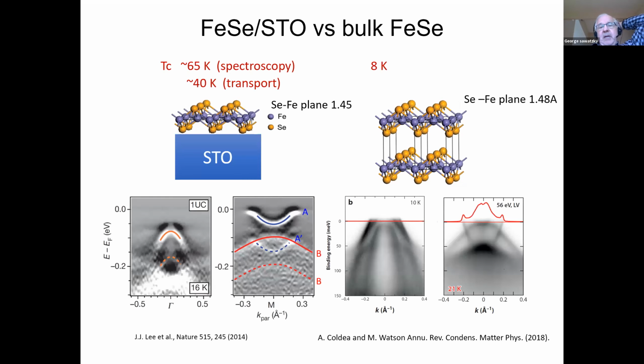Anyway, I should mention the double layer because this is one of the big problems, of course. We all have problems with what actually the structure is, what actually the chemical composition is. Even in the case of iron selenide, one claims from Cava's work that the real line phase is something like 1.01 iron to selenium. So there's extra iron in there, a very small amount, which gets me to think about your very low concentrations of manganese, for example, that really affect the superconductivity and the behavior of your 111 crystals, which, of course, are very nice crystals. The iron selenide on STO as a thin film or as a monolayer is even much more difficult.